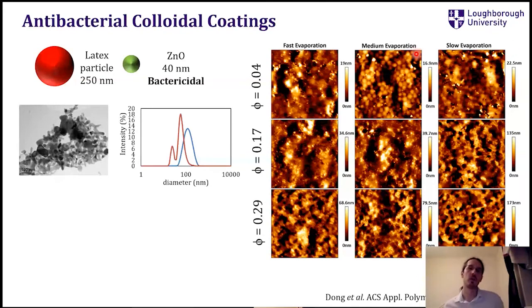So what she saw is that when you blend zinc oxide, and these are again atomic force microscopy images, basically when you have enough zinc oxide, you can see the round things here, these are the latex particles, and then these features here, this is a structure that is just made of zinc oxide nanoparticles. So for enough concentration of zinc oxide nanoparticles, we get a surface which is just covered by zinc oxide nanoparticles. We don't see any latex. It seems to be some kind of, like we call it, a grid structure with some holes in there. And that's probably because the latex particles underneath are templating that structure.